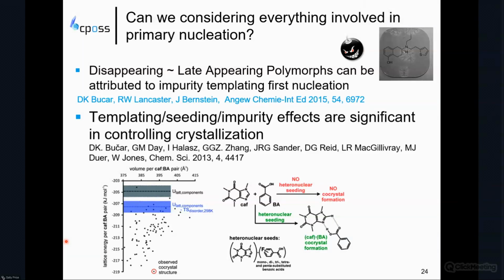There is an interesting paper showing this rather surprising effect, led by my colleague Kresho Bukhar, who had been absolutely convinced that caffeine should form a co-crystal with the benzoic acid. But he couldn't make it happen. He got Graham Day, who did the CSP, and yes, it should be forming a co-crystal. That was going to be much more stable than crystallizing as the two components. Then Kresho had the idea and introduced some seeds of fluorinated benzoic acid. And soon in his lab, he was able to produce the co-crystal, the one that had been predicted, regularly without introducing the seeds.